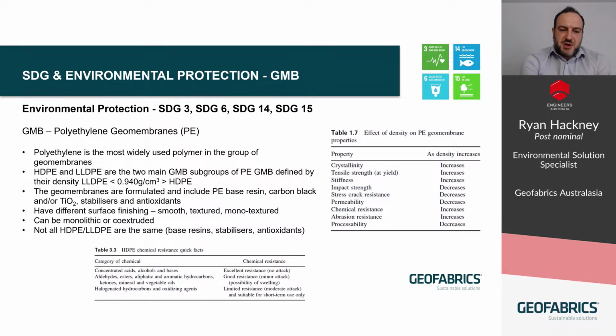With polyethylene geomembranes, as I mentioned, they're the most widely used polymer in the group of geomembranes, and HDPE, which is high density polyethylene, and LLDPE, which is linear low density polyethylene, are the two main geomembrane subgroups of that family. The difference between the high density and the low density is defined by its density, and the cutoff point is 0.940 grams per cubic centimeter. Anything less than 0.94 grams per cubic centimeter is classified as a low density polyethylene, and anything higher than 0.94 grams per cubic centimeter is classified as a high density polyethylene.